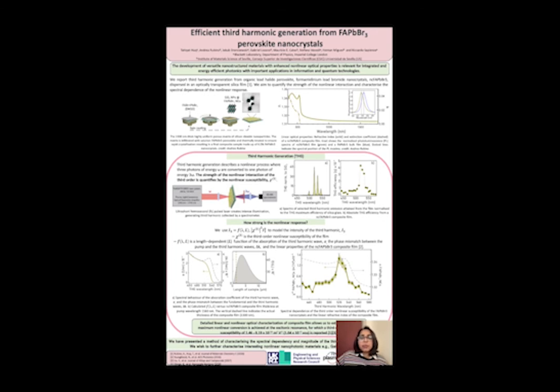By excitation with a pulsed femtosecond laser, we observed efficient third harmonic conversion in a wide spectral range in the near-infrared, with maximum conversion near the excitonic resonance of the nanocrystals, where the electron density of states is largest. We evaluated the maximum third-order nonlinear susceptibility of the nanocrystals by fitting an analytical model to the experimental third harmonic data. This model takes into account the optical properties of the sample, as well as the phase mismatch and absorption